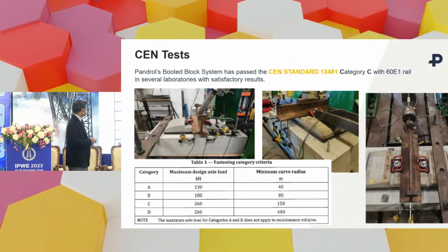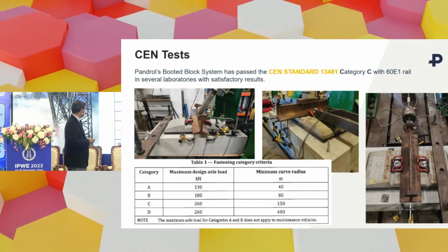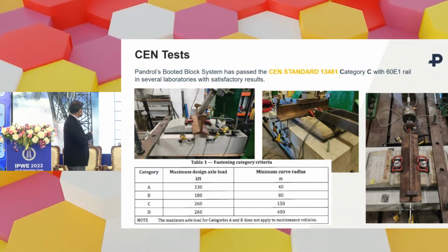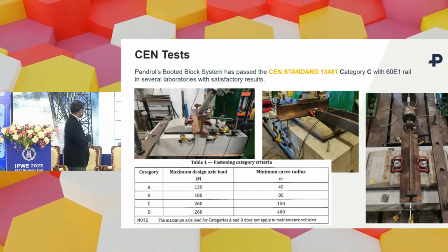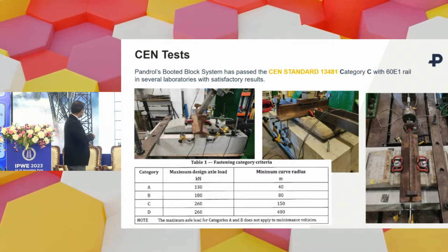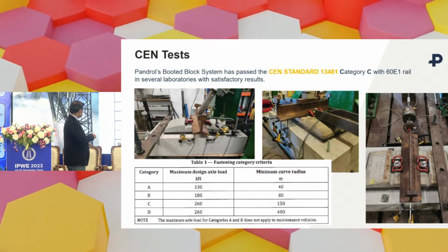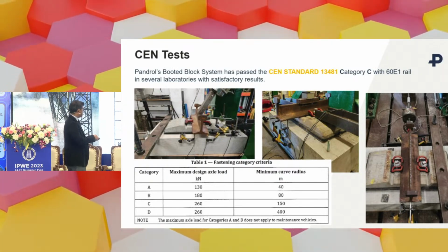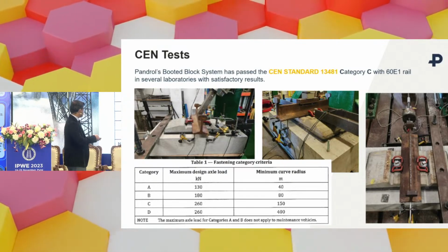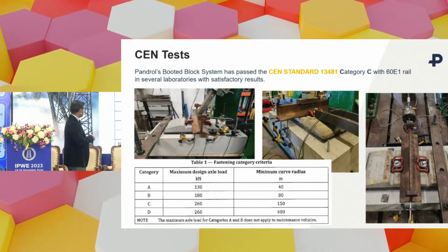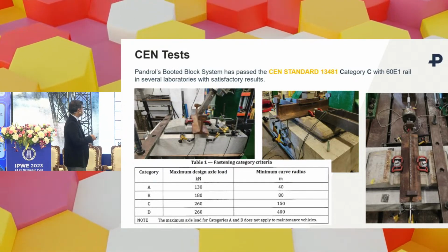It has been tested. Here's a table which shows that the system is tested as per category C, which is 26 ton and 150 curve radius. So this is what the system has been tested for. And the fatigue cycles are 3 million, which the system has been tested for.